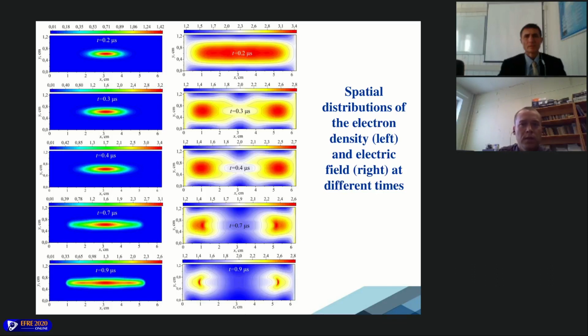In the electric field, it is seen that at first the plasma density is low and does not disturb the electromagnetic field. At time 0.3 microsecond, the maximum plasma density is this value, and the applied microwave electromagnetic field begins to be significantly modified by the plasma. Moreover, the effect observed is similar to a dielectric sphere in a constant external electric field. The polarization effect tends to enhance the electric field at the poles of the plasmoid in the direction of the field.